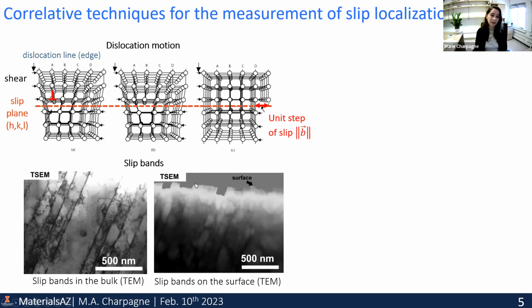Now that's looking in cross section again. This is our surface of the material, and we cut a cross section, and we clearly see the extrusions that are formed by the different slip bands resulting from a process in the bulk of the material. So in a nutshell, we have dislocations that glide in the bulk and exit on the surface and create mini steps. I want to make very clear that these steps are not cracks at this point, they're just extrusion steps, and we'll see that some of them eventually turn into cracks, but not all of them.